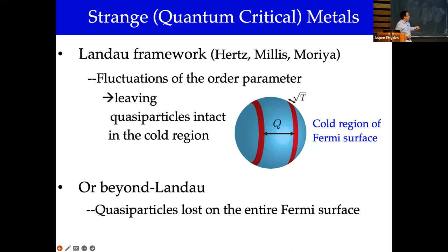And as a result, if you ask the question, what are the fermions doing when they are coupled to such critical fluctuations, much of this Fermi surface will still contain quasiparticles because there's no phase space to connect this fermion with some other fermion in the shell that's living in the vicinity of the Fermi energy. So in this canonical description of quantum criticality in metallic settings, quasiparticles would again be staying intact for much of the Fermi surface. But if we want to end up with something that resembles strange metallicity, one way to go beyond that description is that somehow quasiparticles get lost on the entire Fermi surface.